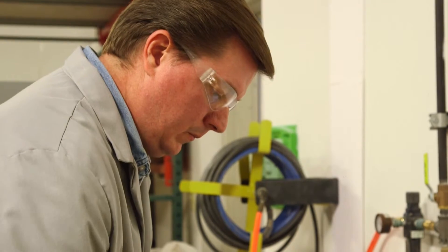The ceramic plate is brushed with a third coating, yielding five to six mils thickness. Since ceramics have similar thermal expansion to the coating, this thickness can be used even with thermal cycling.